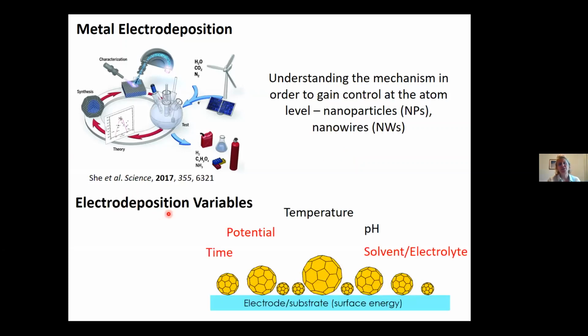What's nice in electrodeposition, although you could say in some respects it is a caveat because it's almost got too many variables, is you have a whole host of different parameters that you can control to tune the structure that you get. And we've played around with pretty much all of them. So you'll have an electrode substrate, the surface energy of which will dictate whether you form nanoparticles or thin films over the surface. We're going to be working with carbon surfaces here, so low energy substrates. You've got potential as a variable, time. I'm going to talk towards the end of the talk about some of the work we've been doing on solvent, electrolyte, temperature and pH.